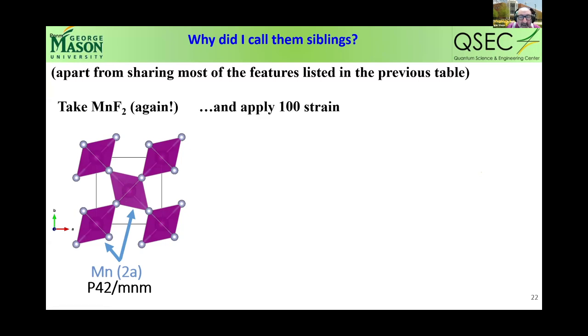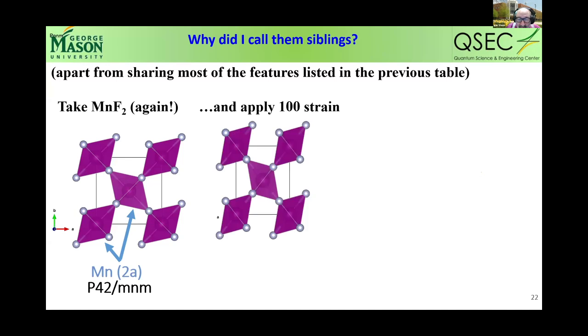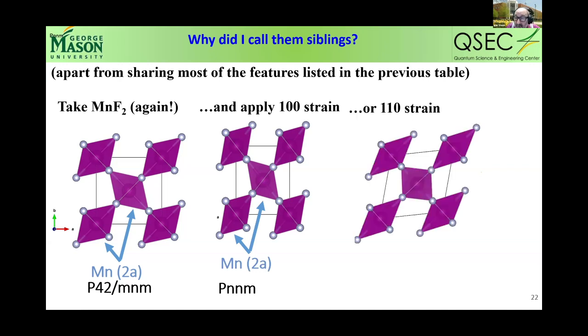That's a known fact. Now I apply 100 strain. 100 strain changes this to an orthorhombic structure, but the symmetry operation, the 4-fold screw axis in this case, which maps one manganese onto the other, remains. So they are still the same, and also 2A incidentally. But if you apply 110 strain, even infinitesimally small, then this symmetry is destroyed. And now I have CMMM positions different from the one before, although it's also orthorhombic. Now I have 2 different manganese. One is 2A and another is 2C.